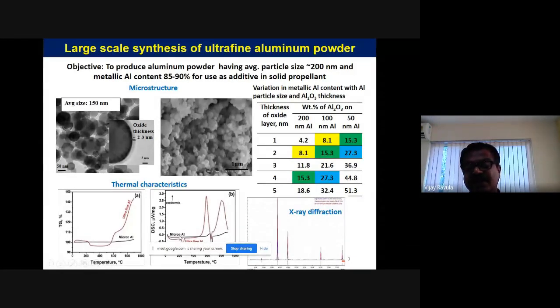If you see the micron-sized one, the black one, it is directly melting, it's not even burning. Whereas the nano-sized one is getting oxidized, it's burning, and it is releasing heat, and that heat can be used in any propellant, so fast. But the problem is, the finer the metal powders, the more pyrophoric they become. Even if you expose them to air, they burn and get oxidized. So the shelf life will be very, very poor.